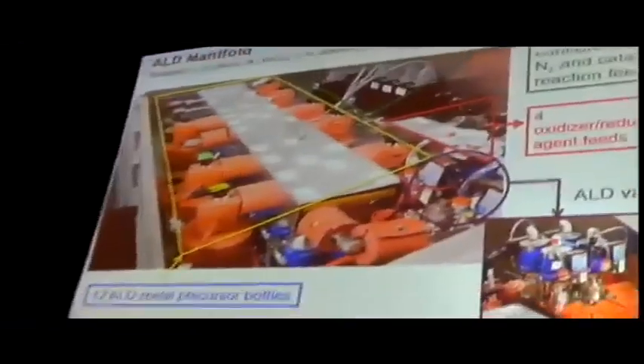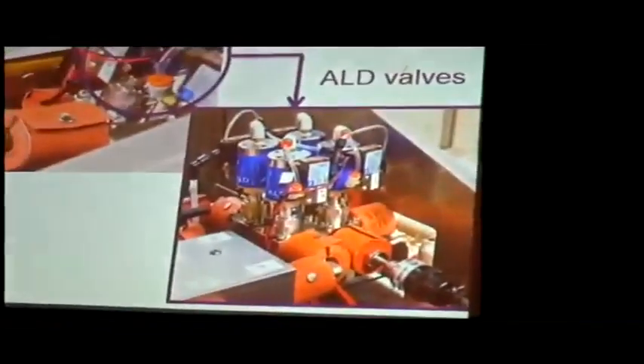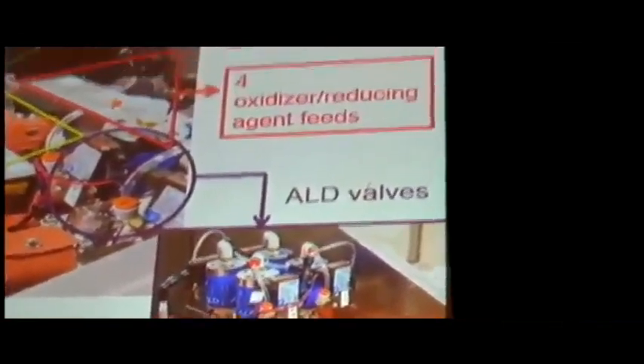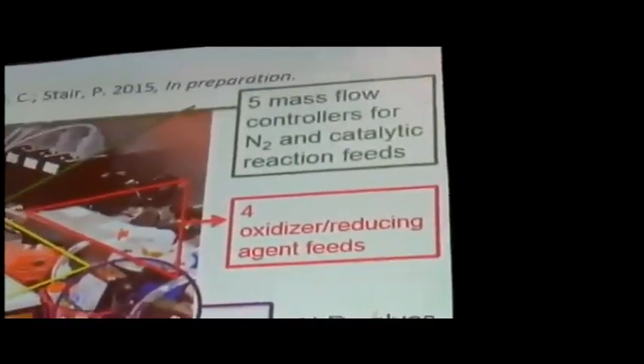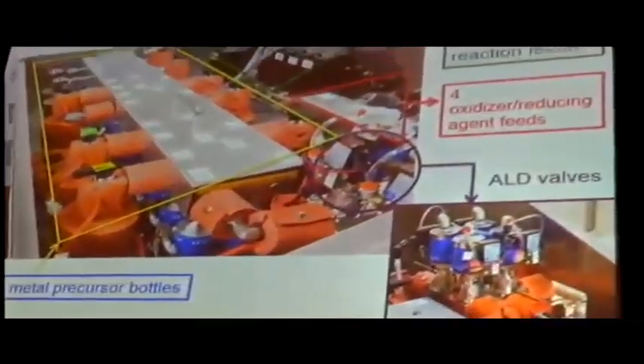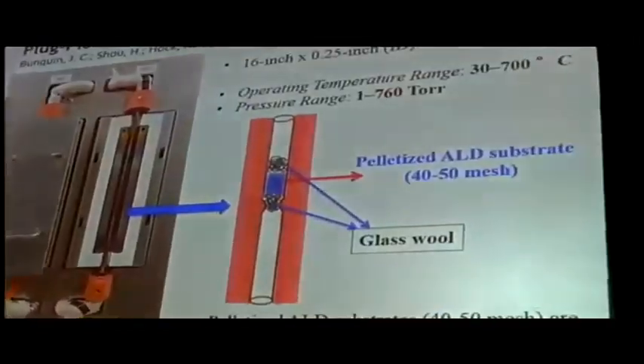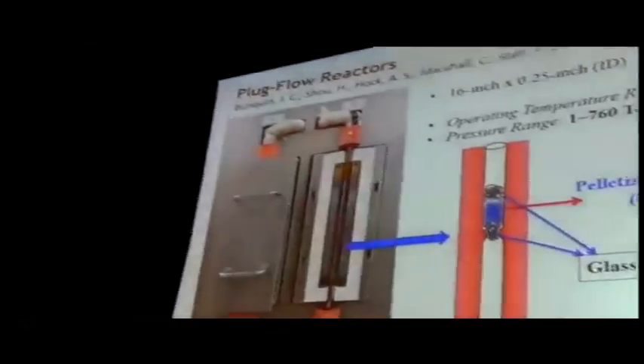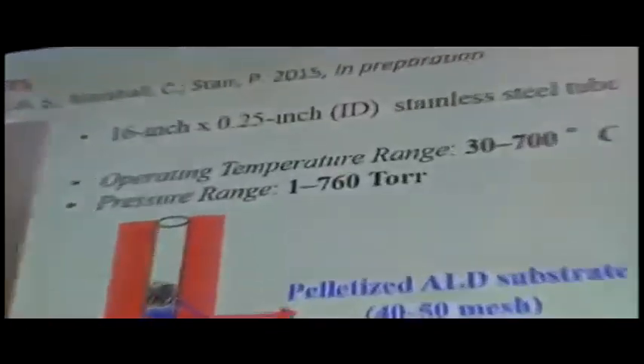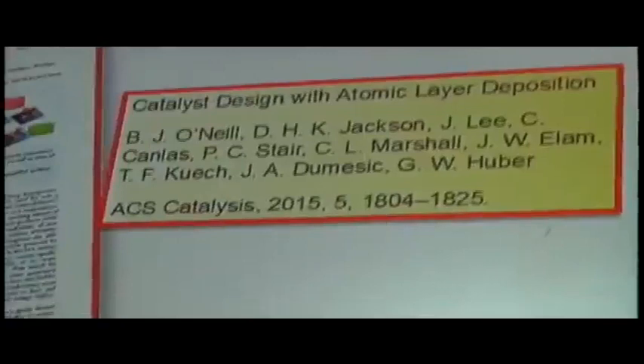We've shown here the manifold that we've got. As I said, we've got up to a dozen metal precursors we can put in here. We can control whether we do the decomposition using oxidizing or reducing conditions. And we've got a whole series of different gas phase feeds, such as ethane, ethylene, propane, propylene, that will do catalyst testing on these reactors. This is just a little picture of that. I'm sure many of you saw our poster last night on this.